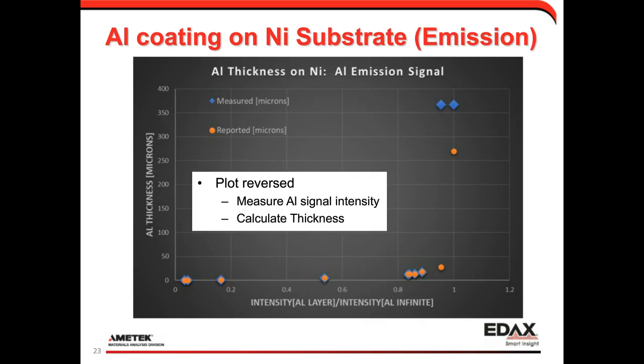These are the results here. Now this plot, because now we're making measurements, and I didn't think to flip this around to match the earlier plots. We've got the signal intensity ratio on the x-axis, and we're getting the output aluminum thickness measurement in microns on the y-axis. So it's reversed from the beginning, and we're measuring the aluminum signal intensity in this case and calculating thickness. The reported values for the measurements are in the orange circles, and the measured results are in the blue diamonds.